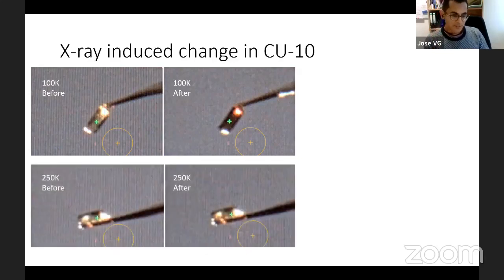If you irradiate the material at 250K, there is no change. And this change is metastable, so after irradiation at 100K, this can live for several hours. I think the maximum I detected was around 11 hours.